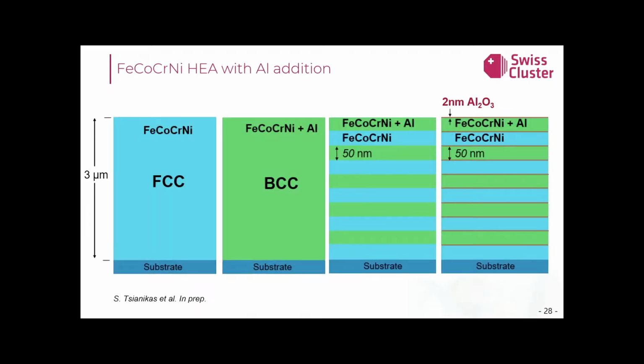Going towards more exotic materials, we also work with high entropy alloys. This is an iron, cobalt, chromium, nickel alloy, which yields an FCC coating material all the way to 3 microns. And if we add aluminum, then this turns to BCC, with the same composition. And then we do the same. We do a 50 nanometer bilayer composition of FCC and BCC, without and with the introduction of 2 nanometers of aluminum oxide by ALD.